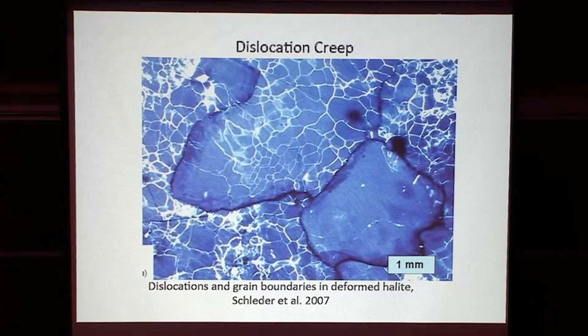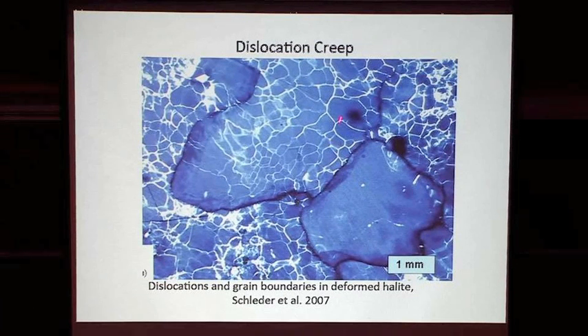And as a consequence, during dislocation creep, the grain size is, if not reduced, at least maintained, because grain growth competes with the fact that grains are breaking up along these dislocation trains.